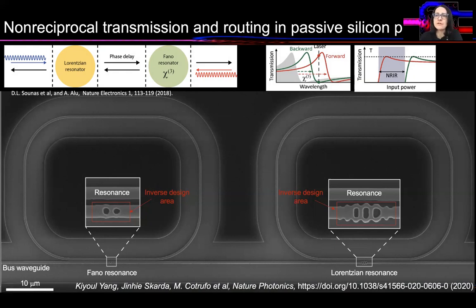which was based on the idea from the group of Andrea Alù at City University of New York, where the main idea is to use a cascade of a Lorentzian and Fano resonator to enable different coupling to the circuit in forward and backward direction. And as a result of the intrinsic nonlinearity in the system, in this case, Chi3 nonlinearity, transmission characteristics of the system would exhibit different shift in the forward and backward propagation direction as a result of different coupling to the structure. And as a result of that, at the laser frequency, you would have strong transmission in the forward direction, small transmission in the backward direction.